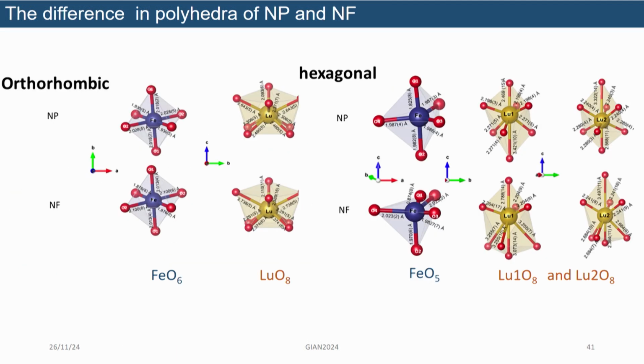Now, next we tried to see what is the distortion in octahedra. So, using Rietveld analysis, we also checked the bond lengths here. It is a powerful tool, X-ray diffraction is a powerful tool, you can do so much with that. So, we tried to see what is the distortion in terms of orthorhombic and hexagonal, and we did find that there is considerable distortion which may contribute to the physical properties, because the structure is very much driven by the bond lengths and other things, and the physical properties are related to the structure.